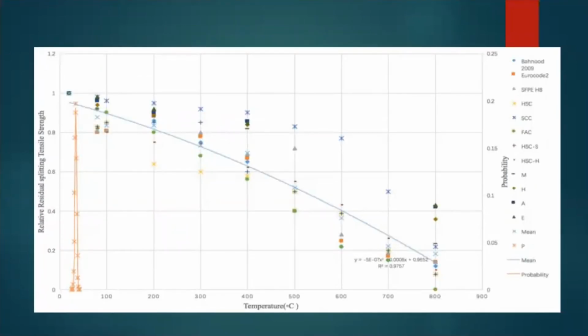According to the average of relative residual splitting tensile strength on every temperature, the mean trend line can be drawn. It can be seen from the figure that the splitting tensile strength after heat decreases with temperature increasing. Additionally, the high performance concrete drops fast and self-consolidation concrete shows the gradual reduction in terms of properties of splitting tensile strength after heat.